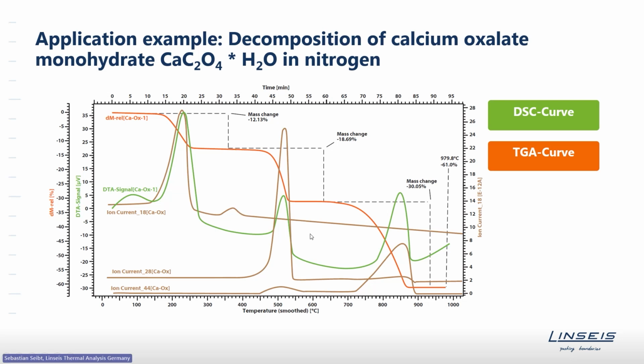by TG directly, and that's it. The other ones are the loss of carbon monoxide. So this is the monitor of the mass of carbon monoxide. So you have a huge peak during the second step, which is the release of carbon monoxide. And the lower line here is carbon dioxide, where you see a low effect during the second decomposition step and a big peak during the third step, dioxide at least. So that's how an experiment looks like if it's coupled to a mass spec.